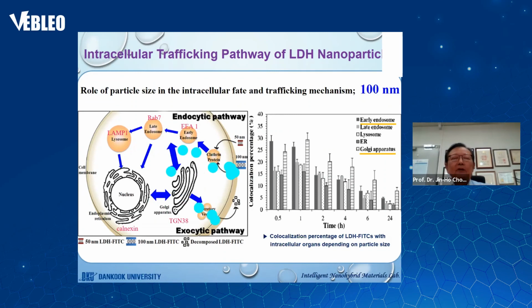In case of 100 nanometer LDH nanoparticles, the particles were primarily co-localized with the early endosome at 30 minutes, as you can see here in the right-hand side. And then apparently a high amount was found in the Golgi complex compared to the lysosome after 24-hour incubation. This is an indication that many of the particles do not go through the well-known endosomal lysosomal pathways. Most of the particles seem to follow a direct exocytosis pathway represented by early endosome, Golgi, rather than escaping typical endosomal lysosomal degradation, implying an important role of the exocytic pathway in the trafficking of 100 nanometer particles.